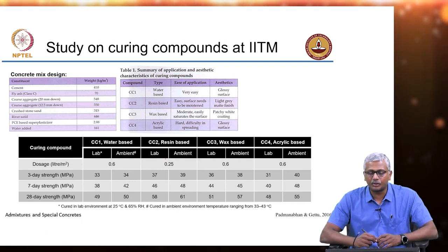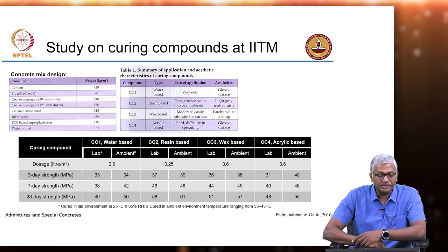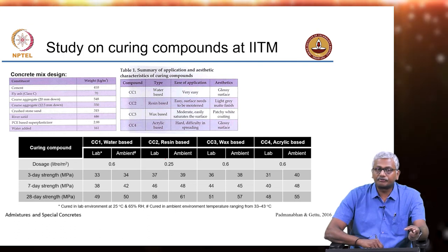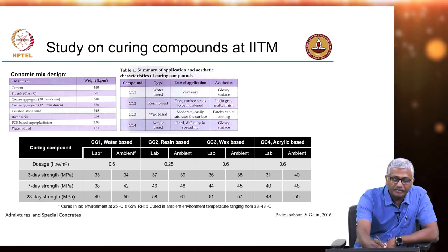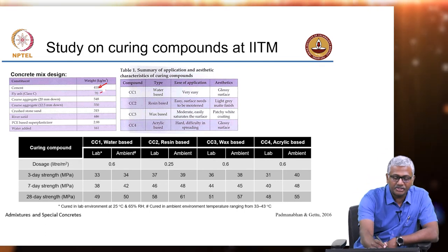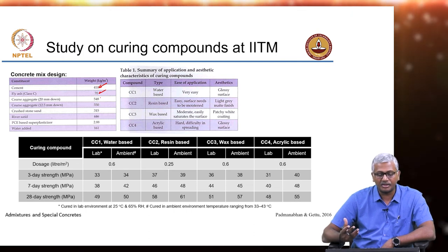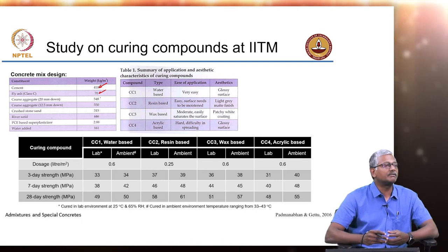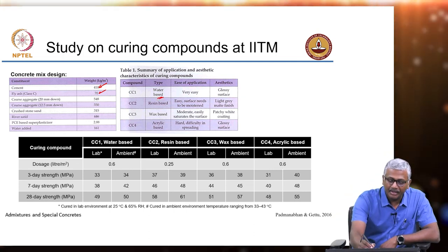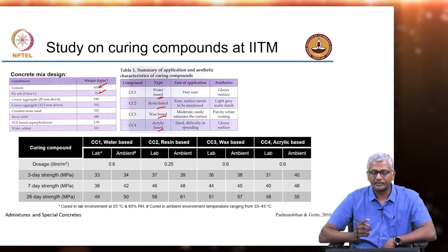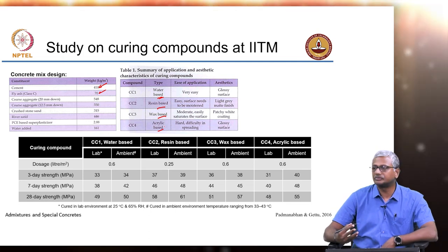We have done several studies on curing compounds. One is a study done by a student where they looked at the use of curing compounds for tunnel segments. The cement weight is about 410 kg, fly ash is 70 kg, and the water-cement ratio is roughly 160 divided by about 480, so about 0.33. These are concretes intended to develop a significantly high strength. Four different types of curing compounds were used: water-based, resin-based, wax-based, and acrylic-based.